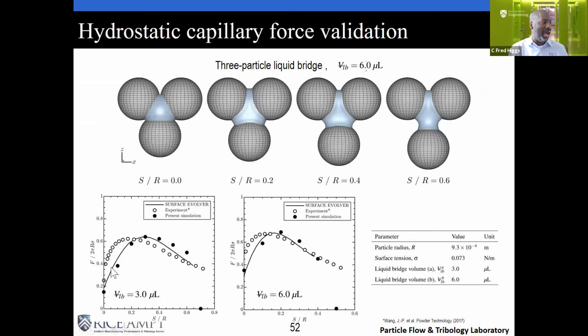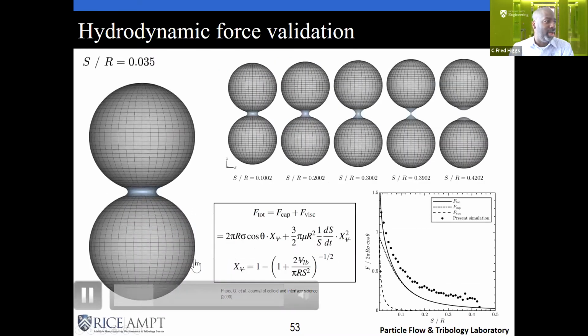And we saw, again, we're reasonable with our simulation, the solid dots there. We actually match closer to this solid Evolver curve, which is a different way that people looked at it, just looking at the energy between particles. We were closer to them than to the experiments. We went back and looked at the literature, and it turns out from the experiments, they had doubts on determining what their spacing was. So we matched another well-known simulation, and the experiments expressed doubts about the true distance and the accuracy of that. So we don't feel too bad about being off, since the experimenters were not totally confident in their distance. But it shows us that we're able to do this.